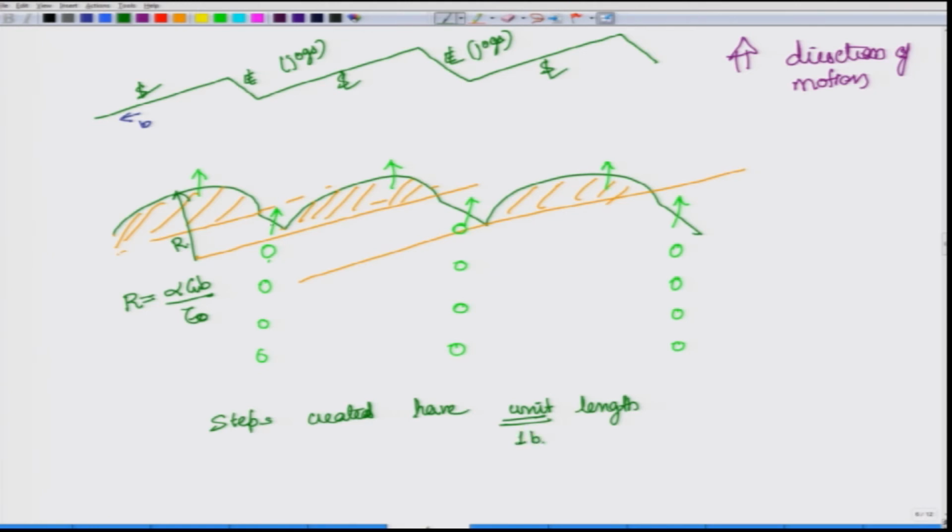Okay. So, the jogs so far we have discussed are simple jogs. Now, we will discuss something about what are called super jogs. So, this is the behavior of a simple jog. Now, how do these super jogs behave? What are these super jogs first of all? As you can realize, the way we are describing, the super jogs would be something larger in size than a jog, and that is true when more than 1 atomic spacing. So, the jogs would have 1 unit length, meaning 1 atomic spacing, but when you have more than 1 atomic spacing, then it is called super jogs.